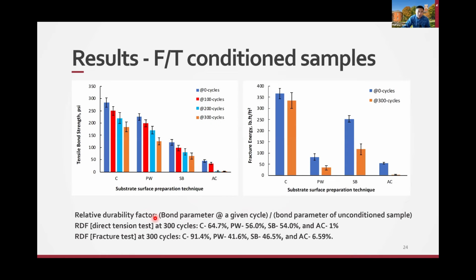In this case, we put the samples in the chamber and do the freeze-thaw cycles. We didn't measure the dynamic modulus, but instead we did the strength test or the fracture test every 100 cycles: 0 cycles, 100, 200, and 300 cycles, as you can see here. As you increase the freeze-thaw cycles, all the strength decreases. This is the tension, and the same thing applies for the fracture energy. We only did 0 cycles and 300 cycles, and you'll see quite a decrease of the bond strength.